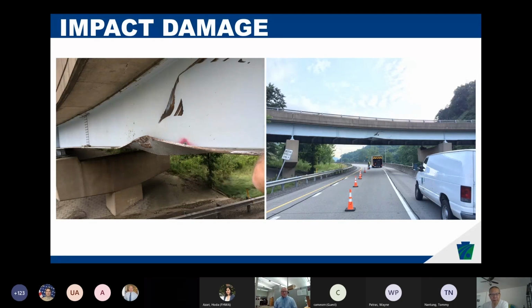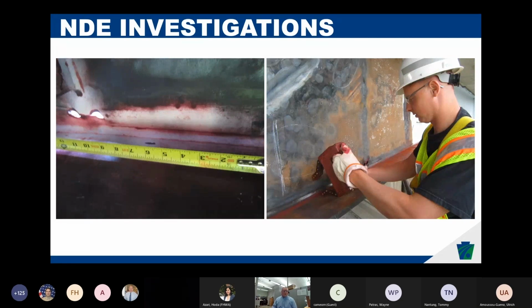Starting with impact damage, this was one of those structures where the bridge isn't too low. A garbage truck forgot to put its forks down when it was exiting the ramp or traveling down the road, and it smacked into the bridge, causing a significant amount of damage. So obviously the bridge was closed, both the overpass and the underpass for traffic. The very next day we did an NDE investigation, applying your typical ultrasonic testing, mag particle testing, and dye penetrant testing, looking at the critical areas to see if we could open the roadways back up. The critical areas being those toes of welds in this case, where it's more prone to crack when it endures a large impact, such as a trash truck driving down the road with its forks up.